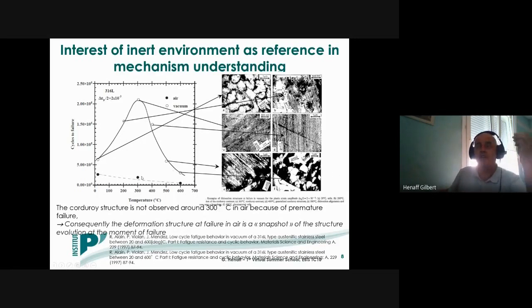But the point is that if you perform the same type of observations in air, you will not observe the corduroy structure at 300 degrees C, because failure will occur much earlier during the fatigue life due to the assistance of the environmental effects. Typically, the deformation internal structure that you would observe in air at 300 degrees C would be only a snapshot of the evolution of the dislocation structures towards this corduroy structure.